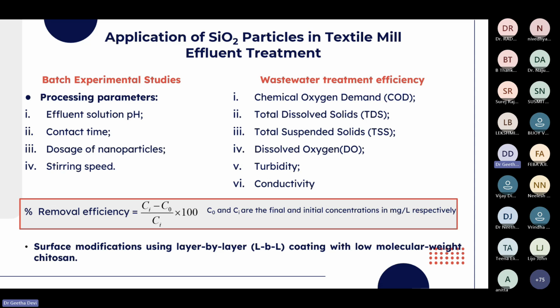using this equation. We have tried the bare silica nanoparticles for the treatment of textile industry wastewater, as well as modified silica nanoparticles, that is, surface functionalization was done using a nano coating over the surface of the nanoparticle with low molecular weight chitosan.